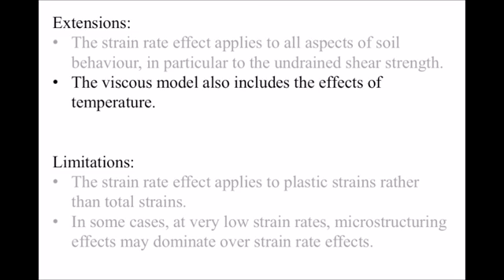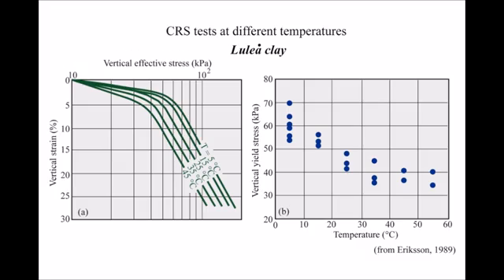Another extension is that the viscous model, the strain rate model, can also include the effects of temperature. And this has been shown by several people, including here, but in particular by Eriksson, who performed CRS tests on the Swedish clay at different temperatures. And the results are shown here. You can see that the smaller the temperature, the larger is the vertical effective stress.